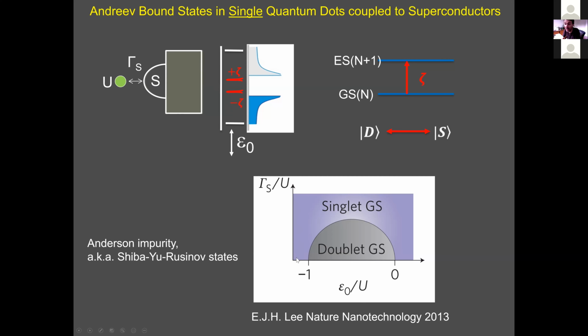And you can see how it comes about. So the vertical axis is the coupling parameter. If the coupling parameter is 0, we just go from 2 particles, singlet, 1 particle, doublet, no particles again, singlet, or holes. And then as we couple more and more, if we couple very strongly, then electrons in a superconductor screen the spin on the dot and make a many-body singlet ground state. So then when the doublet is the ground state, then we add another electron to the dot. Then singlet is the excited state, the state of 2 electrons.